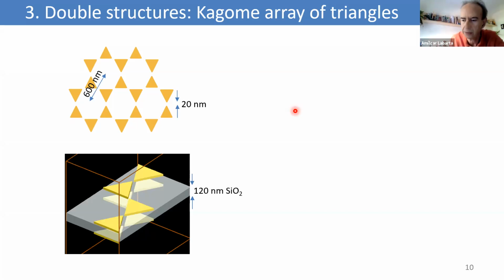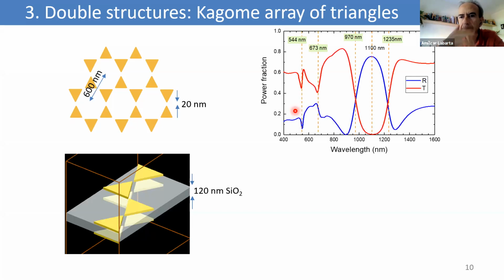Okay, so here you can see the transmission and the reflection, and you see that these two peaks are related to collective excitations of both the active lattice on top and the active lattice on the bottom. And this is interesting because you see a dip in both the transmission and the reflection, and this is not common. And this is probably associated with a kind of dark mode in the system.